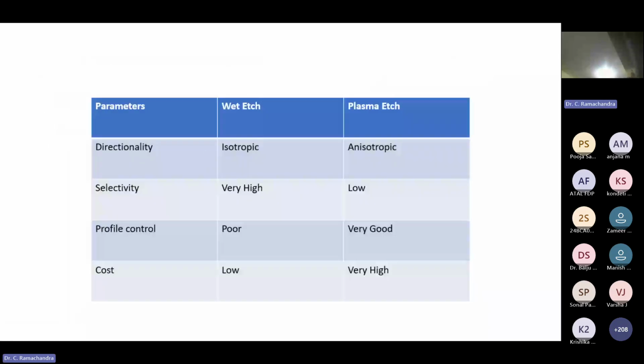So this is a comparison. Wet etch directionality is isotropic. When you come to plasma etch, it is anisotropic. That means I can etch in one particular direction. Selectivity, wet etch provides very high. For plasma it is low to medium. This is a selection we need to optimize in the process. But here profile control is poor because wet etch etches in all directions. Here it is possible to have very good control and sometimes even a 90-degree profile, which is required. As I showed, it is possible only in plasma etching.